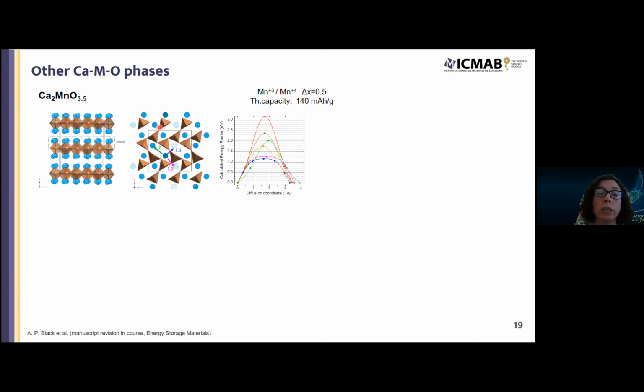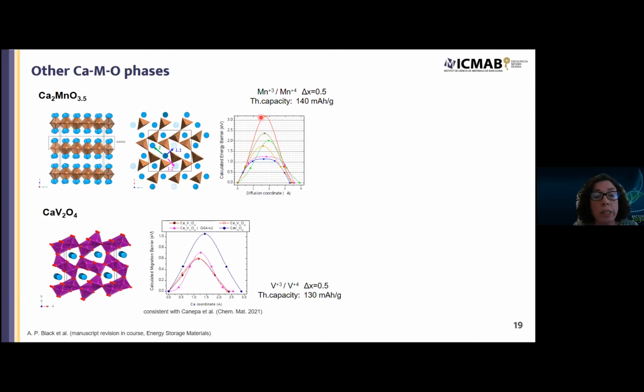And in this case, the coordination of manganese is not octahedral because there are those oxygen missing, so it is pyramids. So she calculated the migration barriers along different pathways, and you see that in this AB plane where the vacancies are, the migration barriers are, I would say, tolerable, about 1 electron volt. And of course, when one considers a migration along the C direction and these perovskite slabs, then the barriers are very high. But still, this was considered interesting for experimental investigation.